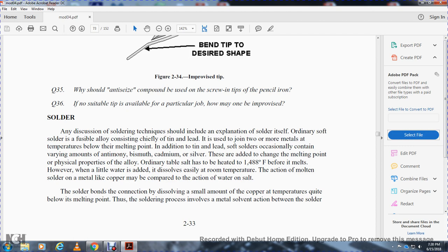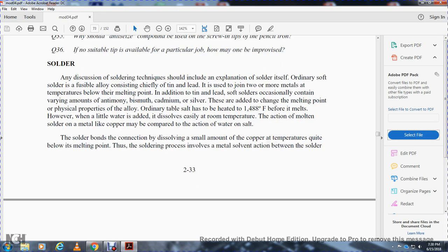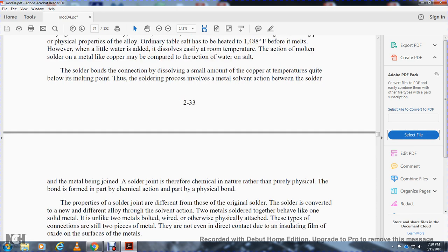Ordinary table salt has to be heated to 1,488°F before it melts. However, when a little water is added, it dissolves easily at room temperature. The action of molten solder on a metal like copper may be compared to the action of water on salt. Solder bonds with the connection, dissolving a small amount of the copper at a temperature well below its melting point. Thus, the soldering process involves a solvent action between the solder and the metal being joined. The solder joint is therefore chemical in nature rather than purely physical.